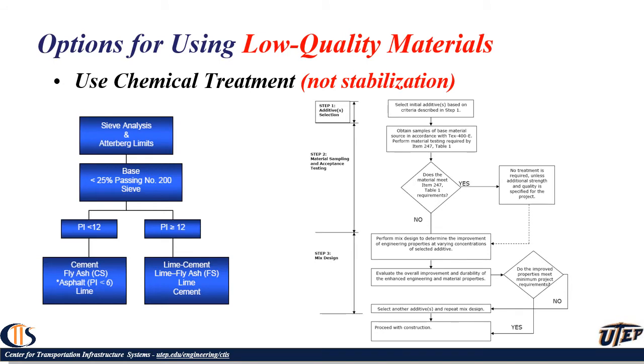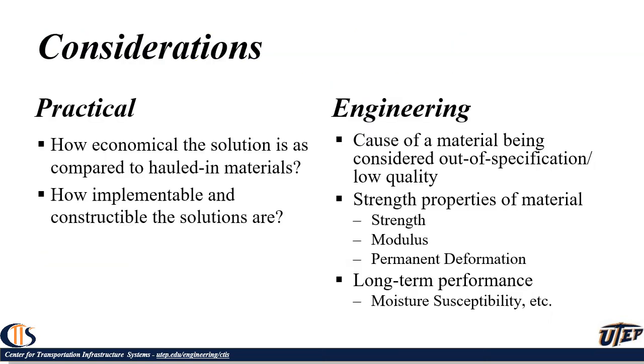For the low quality materials, we primarily consider to use chemical treatment. I use treatment differently than stabilization. Treatment, we are talking about 1 or 2% of the additives being lime or cement. And depending on the liquid limit and the plastic limit of the material, we would decide what type of stabilizer to use. Some of the considerations were practicality, how economical the solution is compared to the hauled-in materials that are high quality, how implementable and constructible the solutions are.